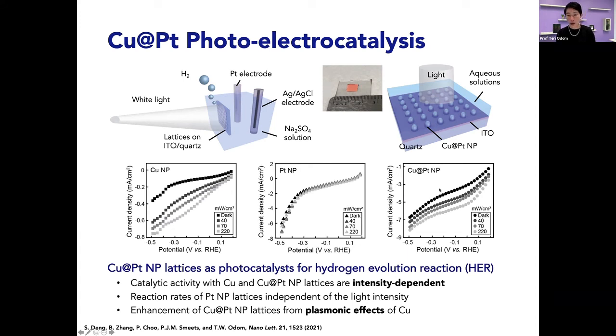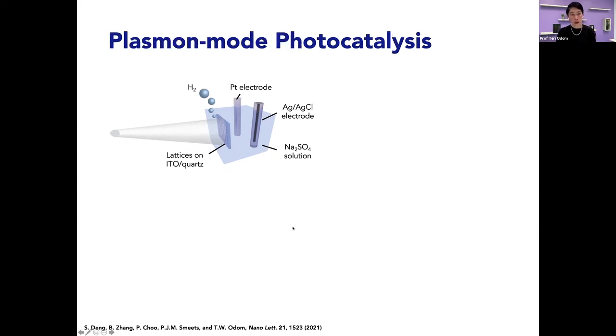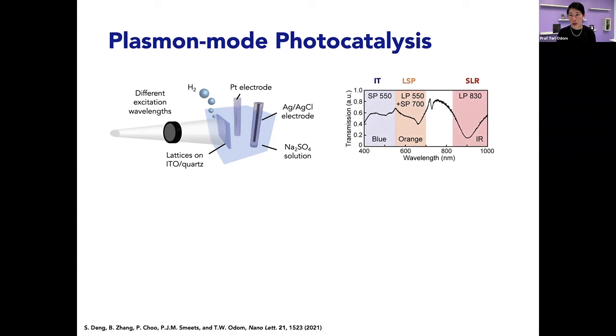the copper core shell with platinum nanoparticles, they depend on intensity. So that makes sense. The localized, the plasmonic aspects are functioning quite well. But if you look at the platinum case, there's no effect. We then wanted to compare the plasmon modes in terms of the SLR, localized surface plasmon, and the interband transition. So we put a filter out so we could test the effects of different excitation wavelengths. So we have a long pass filter at 830, so we can test the SLR, a long pass and short pass, so we can test mostly the localized surface plasmon, and then a short pass.